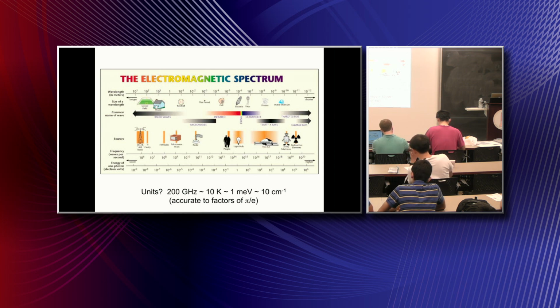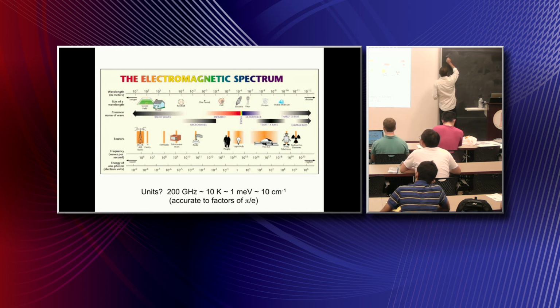Okay, good. Moving onward, talking about energy scales from zero to about half an electron volt, this is generally the energy scale of collective magnetic modes in an ordered system. We call these magnons or spin waves. If we look at even lower energy scales, to about a tenth of an electron volt, these are the collective lattice modes of solids, and we call those phonons. Then at roughly 50 millielectron volts, this is the superconducting gap in cuprates.